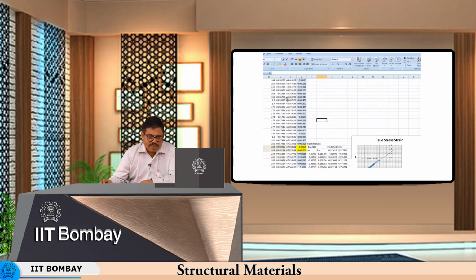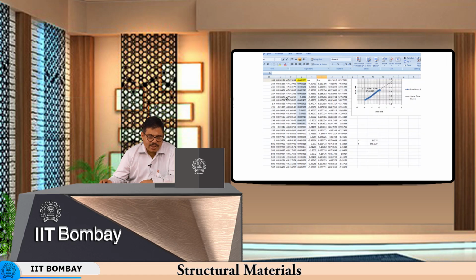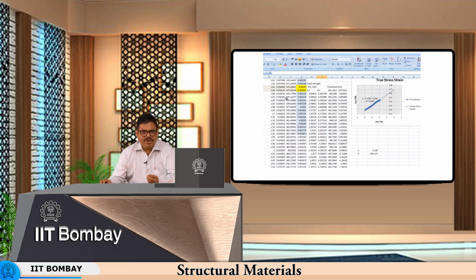So, that is why this equation becomes accurate not at very low plastic strains, but at relatively higher plastic strains, meaning the plastic strain is comparable with the elastic strain in magnitude. So, here the plastic strain is comparable. So, 0.2% was a plastic strain.